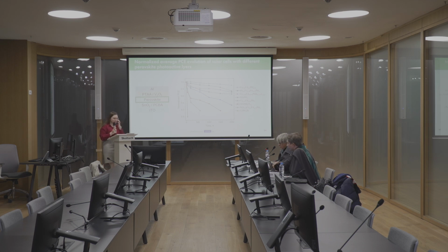Oh, okay, I see. Yes, it's clear. Just to clarify a bit more. So you do not expect that this change is due to the composition and cesium concentration, but you expect that if you create excess of lead iodide, you would get about the same in both, right? If you create in the second one, cesium 0.15, this excess of lead iodide, you would get about the same. Probably, stability, yes. Probably if we add some excess of lead iodide into the stoichiometric structure, there could be some improvements, but at the same time, it should be made quite carefully because we can lose the purity of the phase.